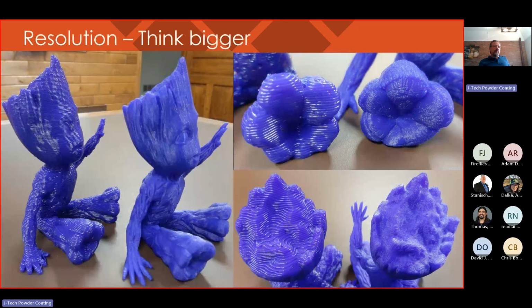So resolution, think bigger. The thicker the layer is, the fewer layers there are to be printed, and you can have a quicker model to produce. So Baby Groot on the right was printed with a typical 0.6 nozzle and a 0.1 layer Z resolution. You can see the fine detail this produces. Even the tree rings and the feet are distinguishable.